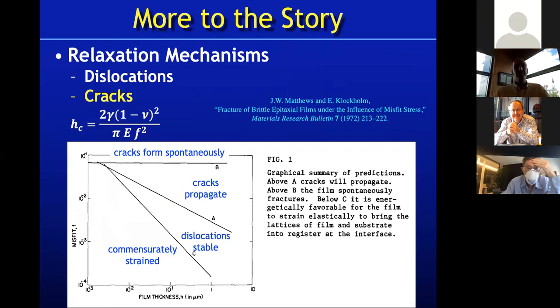And this nice, here's the formulas, and this is now the equilibrium critical thickness for the formation of cracks. It's actually the thickness at which it's stable for existing cracks to propagate in the material. I'll say more about that in a minute. But what Matthews calculated in this nice diagram is, as a function of film thickness, how he would, from an equilibrium perspective, expect the material to behave.